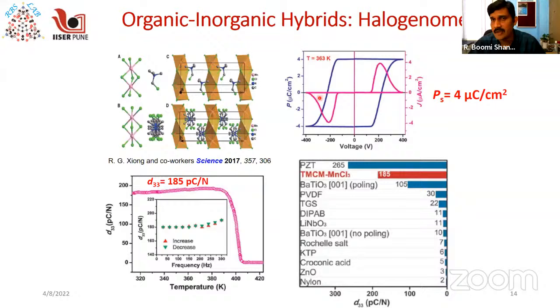The red graph over here is nothing but the leakage current. The leakage current shows almost zero leakage at all the measured voltages. However, it will show a peak at the coercive field because the domain switching happens at that field, which gives rise to a peak at the coercive field. So the signature P-E loop and the J-E hysteresis curves are the signatures of the ferroelectric property